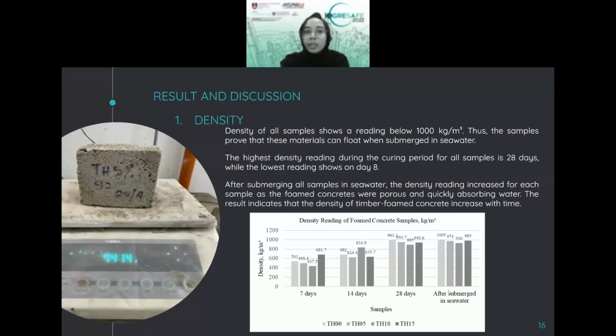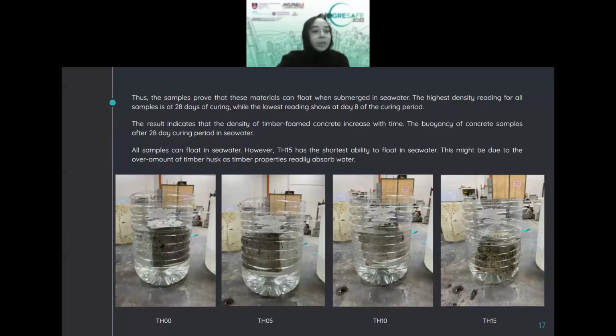And it's due to their properties itself, where foam concrete is very porous, and also the additive itself, timber, can easily absorb water. So this will somehow affect the density after putting it inside the seawater. From here, this shows the situation when I put every material, every percentage inside the seawater. All samples show that they can float. However, TH15, where I use 15 percent of timber, has the shortest ability to float in water. This might be due to the over amount of timber, as timber properties, as we know, readily absorb the water.